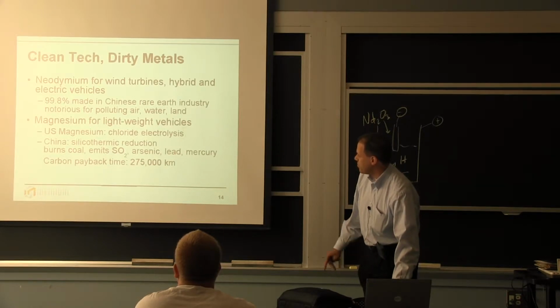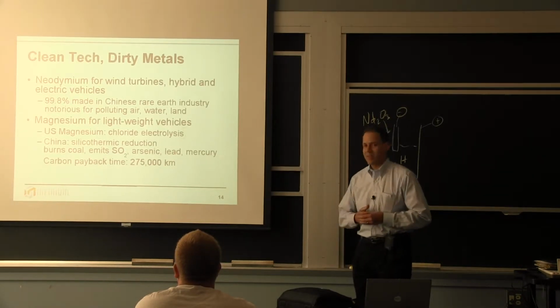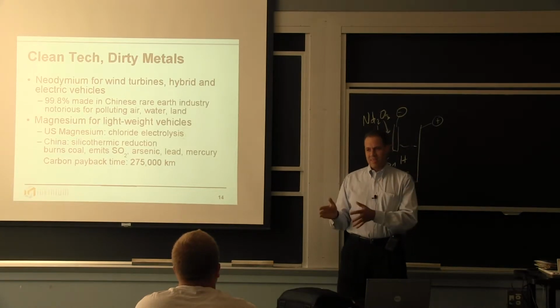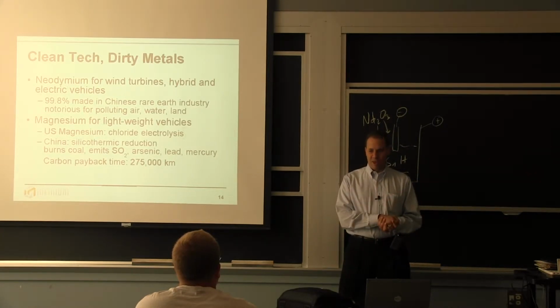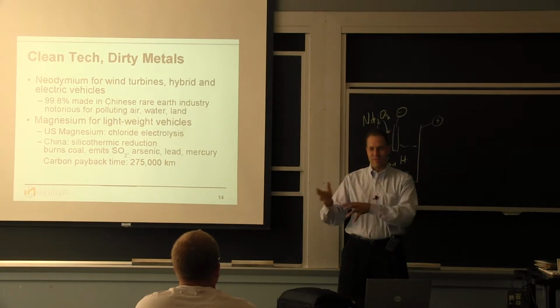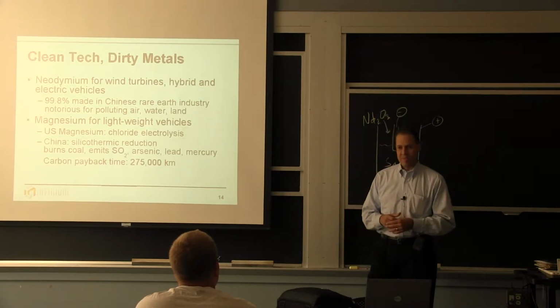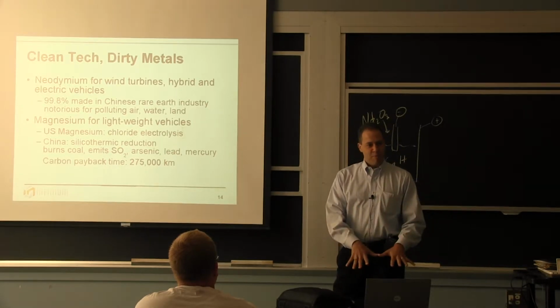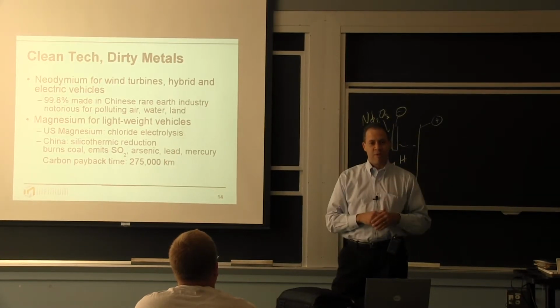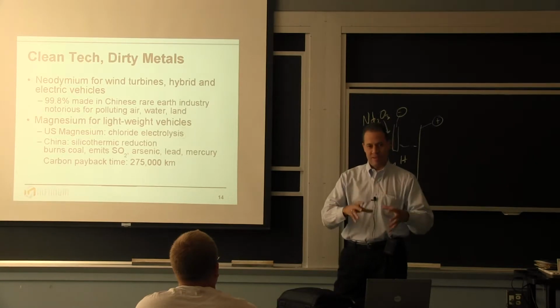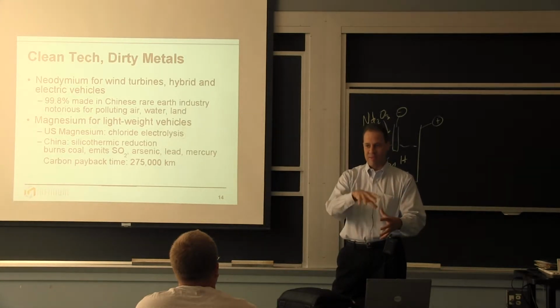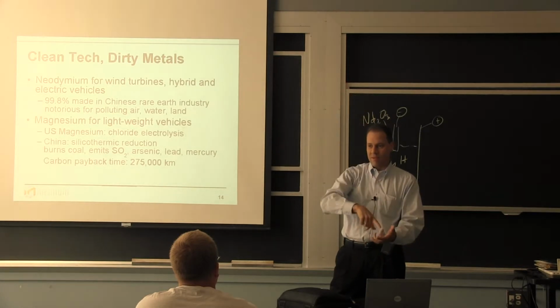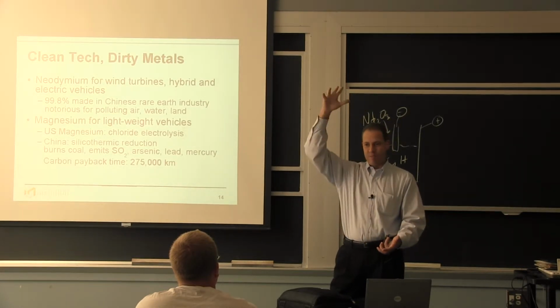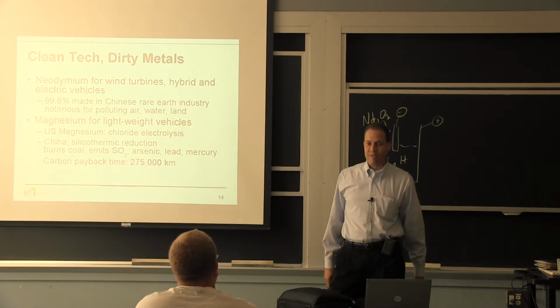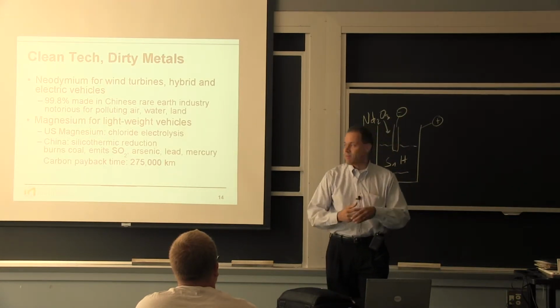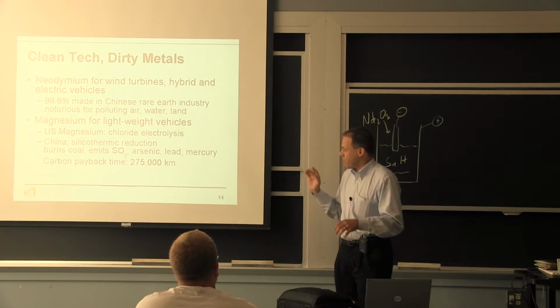Moving on to silicothermic reduction, which, if you know your chemistry, using silicon to reduce magnesium oxide is backwards, right? Magnesium should reduce SiO2, but what happens is silicon has extremely low vapor pressure. Magnesium has very high vapor pressure. So if you put silicon and magnesium oxide in a vessel, pull a vacuum, you'll get a little bit of magnesium vapor pressure, heat one end, cool the other, and you get magnesium transport, and it condenses into solid in the other end. But it takes a lot of energy to drive this reaction. So I'll get back to that in a minute.